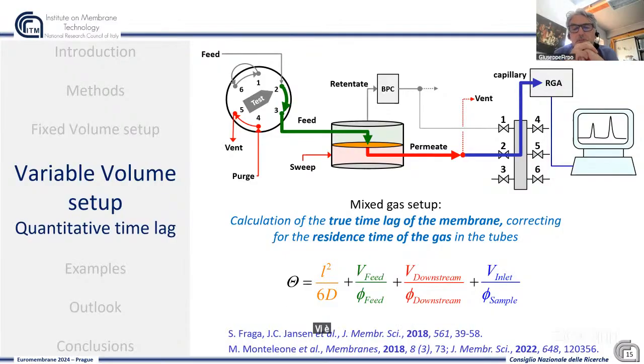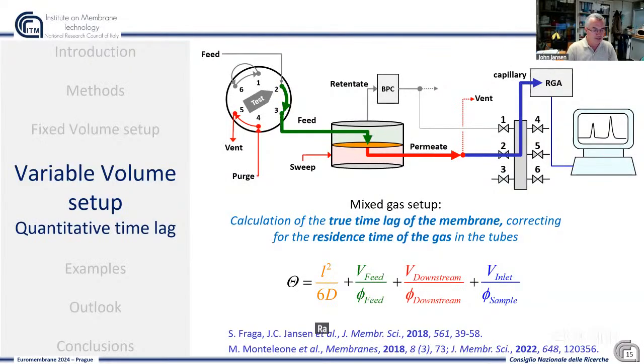Yeah, thank you. Very, very interesting, yes, you can measure also the solubility with this setup, because you measure diffusivity, and it's mandatory to use a residual gas analyzer because gas chromatography, if I understood correctly, is not fast enough, no? No, even the faster ones need 10 seconds or so for every single point.